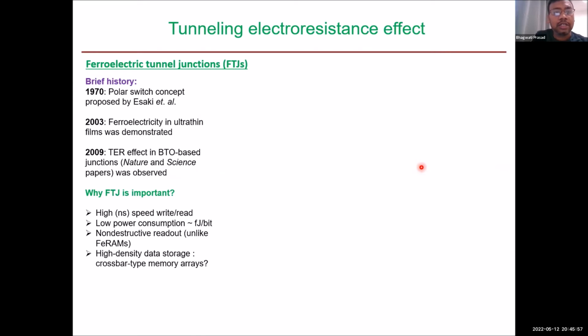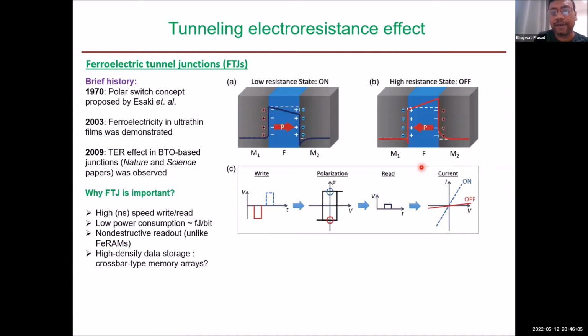Okay, so these are ferroelectric tunnel junctions. What we see in a ferroelectric tunnel junction is the tunneling electroresistance effect. If you use two metals which have different electron screening lengths, and you put a thin ferroelectric insulator between them, the bound charges of the ferroelectric insulator won't be completely compensated by the electrodes. As a result, depending upon the polarity of the ferroelectric insulator, you may see two different barrier heights for the two different directions of the ferroelectric polarization.